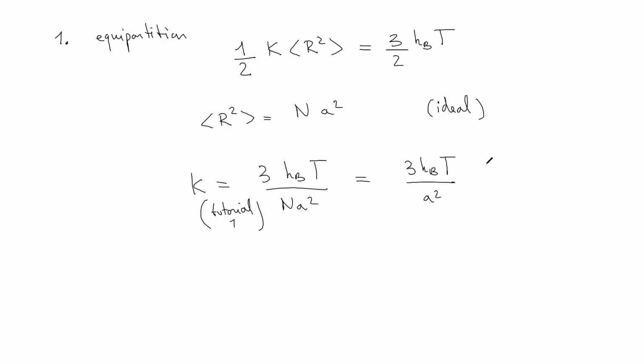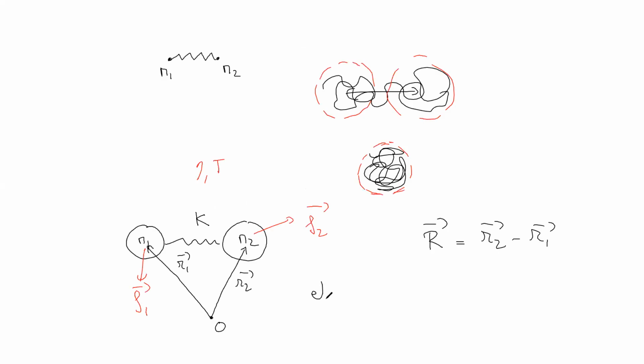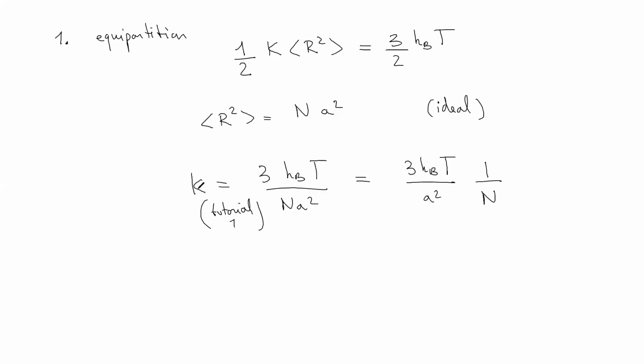And then you have a linear assembly of springs. So the stiffness goes with 1 over N when you are putting them in series. All right, so now K in this elastic dumbbell picture is not random or unknown. It has to be correctly chosen. So dumbbell means halter in French. So it's an elastic dumbbell here. So K here, if you want your model to really describe a polymer, has to be taken to be equal to the entropic stiffness. And then you can recover all the equilibrium properties of a chain.